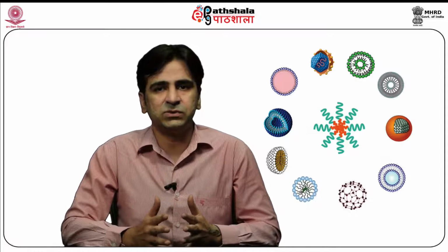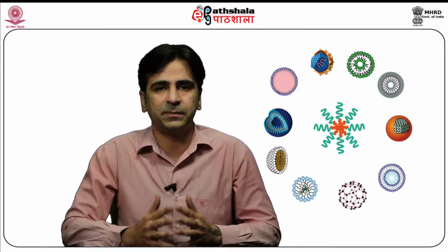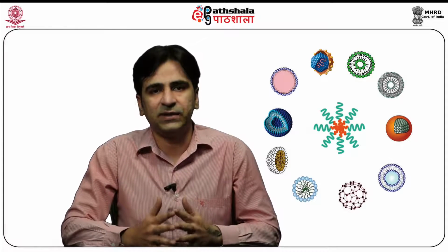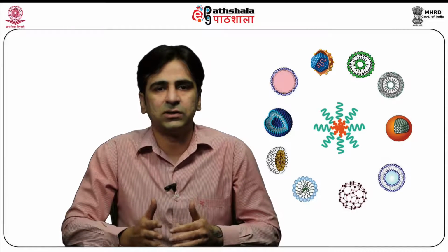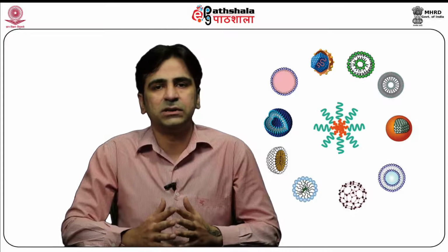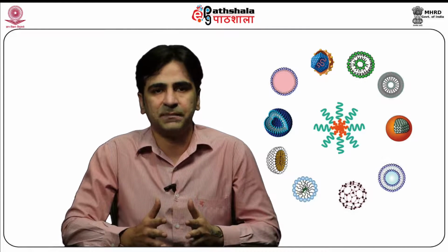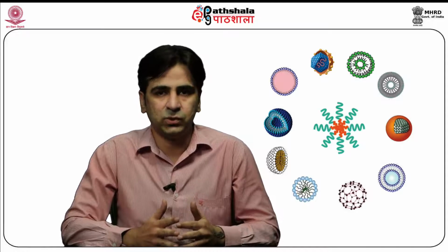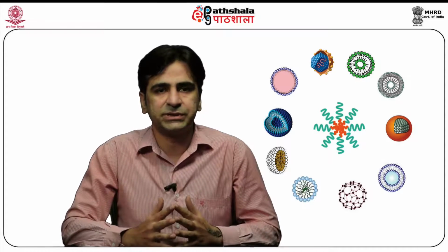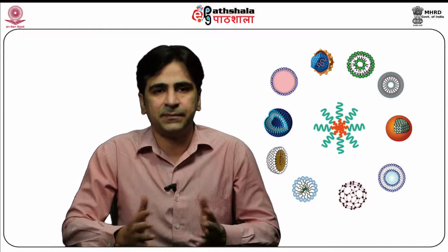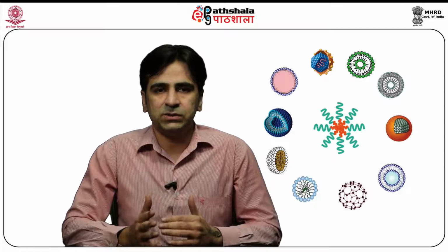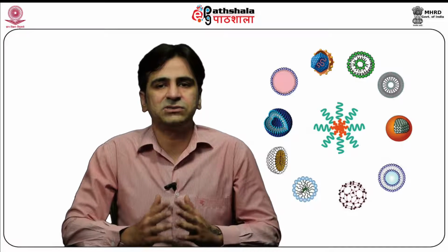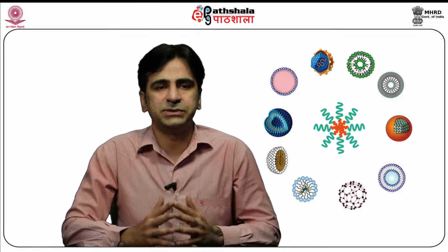Now come to the direct method. Nanosuspension is subjected to centrifugation followed by washing of the pellet and subsequently lyophilization of the formulation. After that, lyophilized particles are dissolved into the common solvent in which both the drug and polymer are soluble, and then samples are subjected to analysis for drug content using a suitable analytical technique. Now come to the indirect method. Under this, nanosuspension is subjected to centrifugation followed by analysis of drug content in the supernatant using suitable analytical techniques.